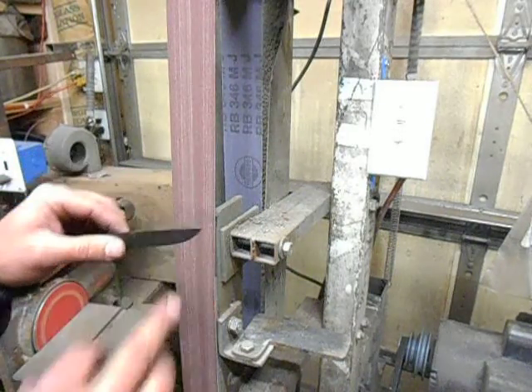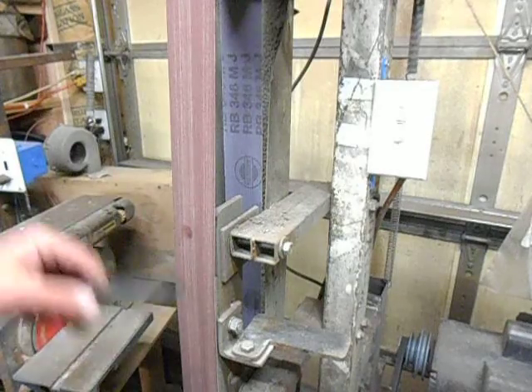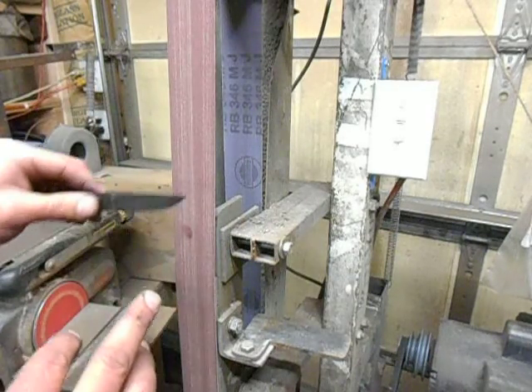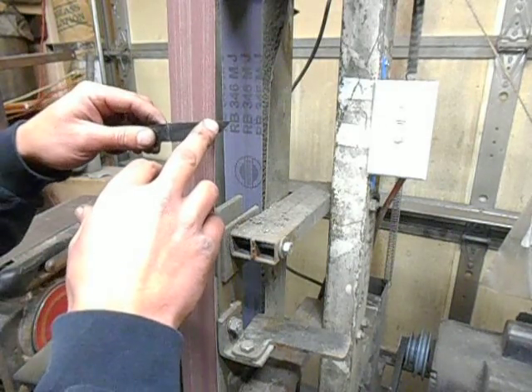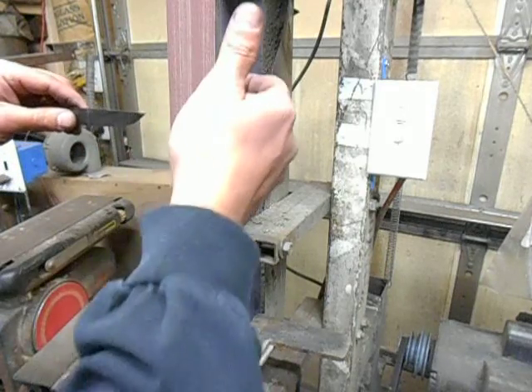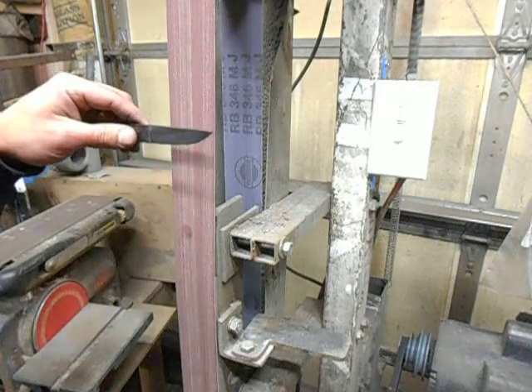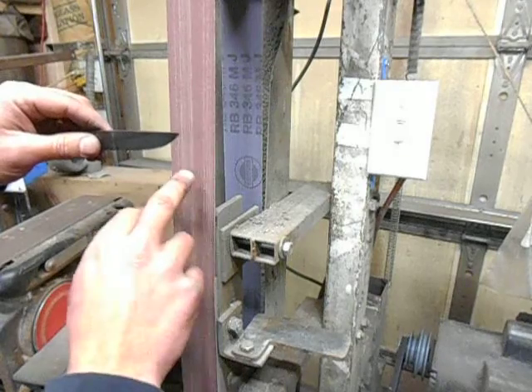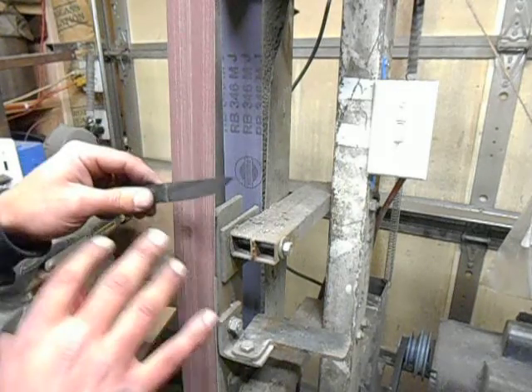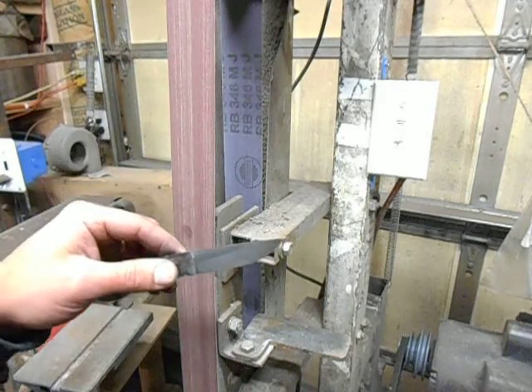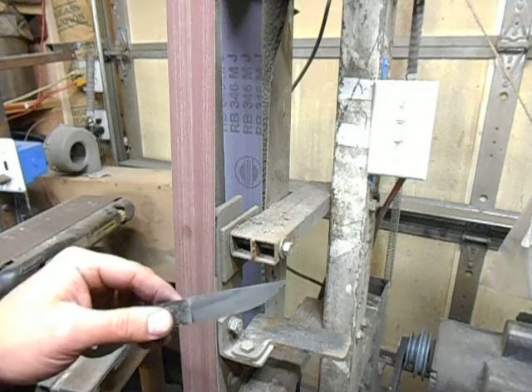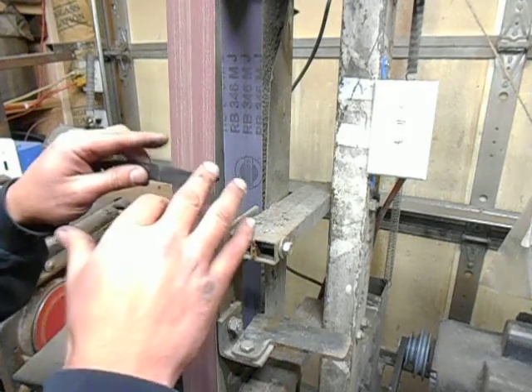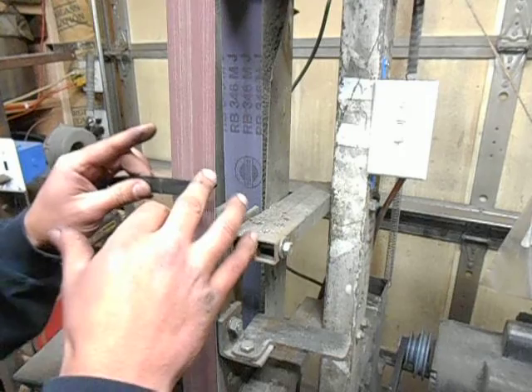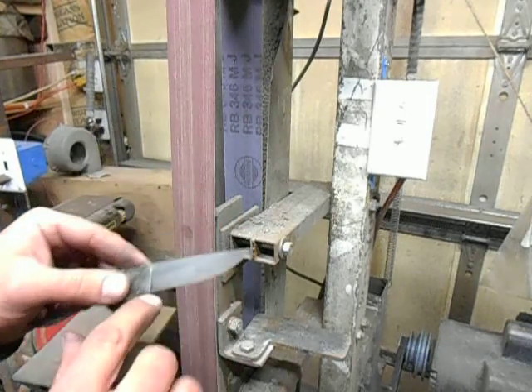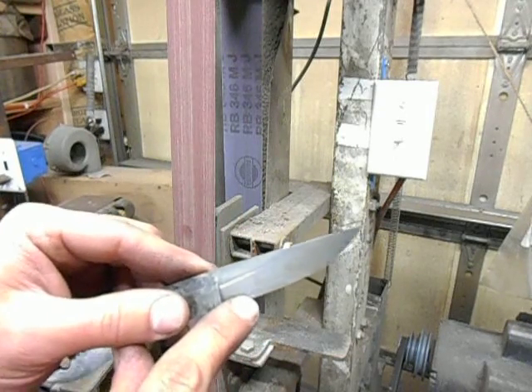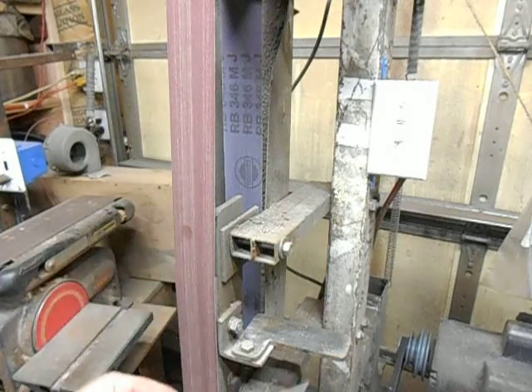Then dunk the blade in water to keep it nice and cool. But a very light touch, with the grit going away from the edge, with a fairly coarse belt to do your shaping, and then finish your sharpening on the stones. Because if you stay in one spot too long, or if you bear down real hard, and you get just the slightest bit of blue on that edge, that knife's junk.